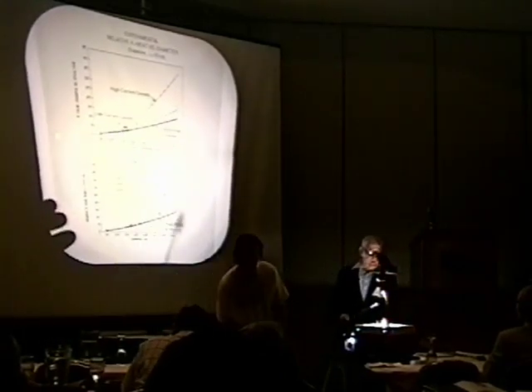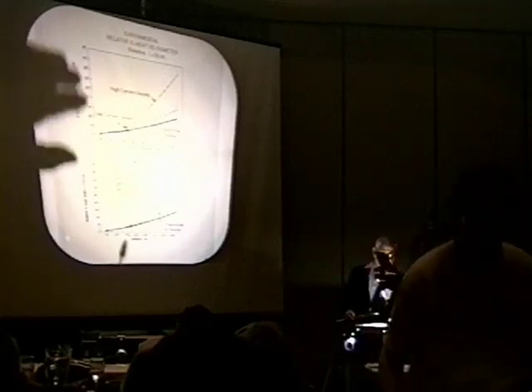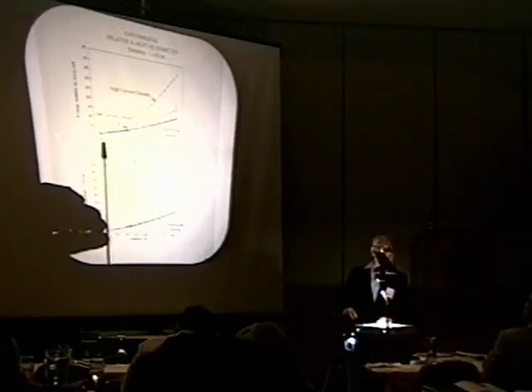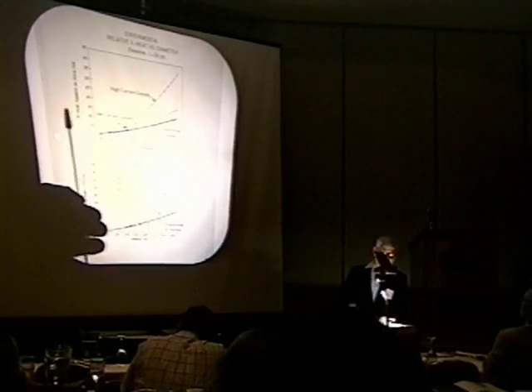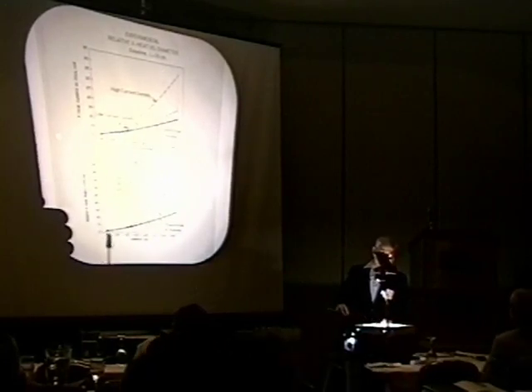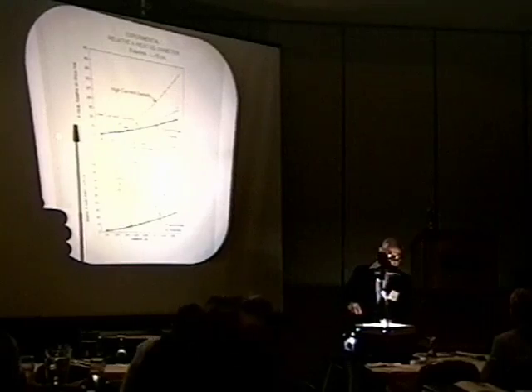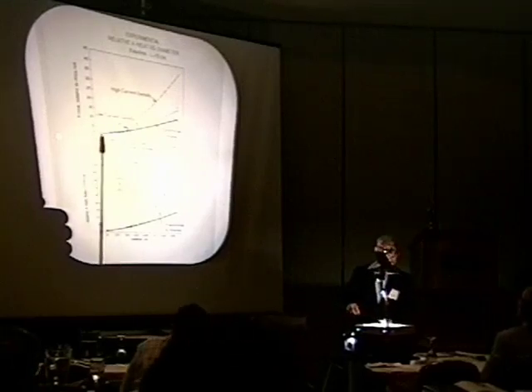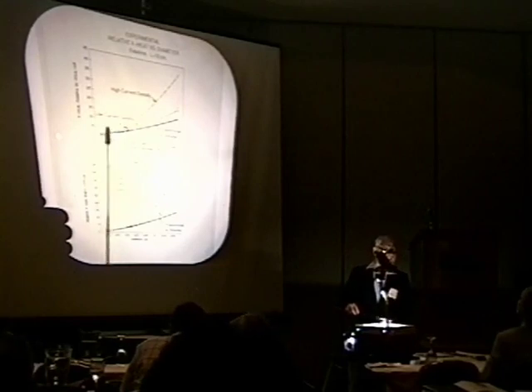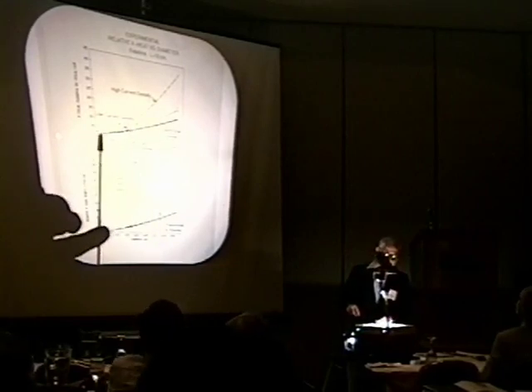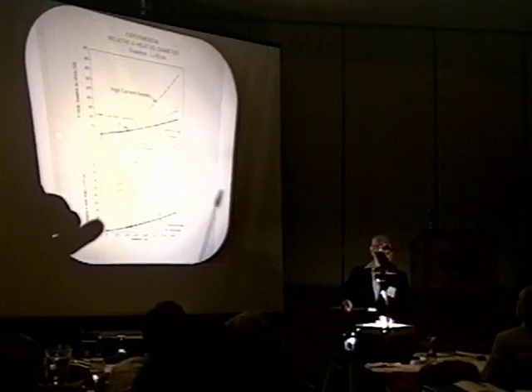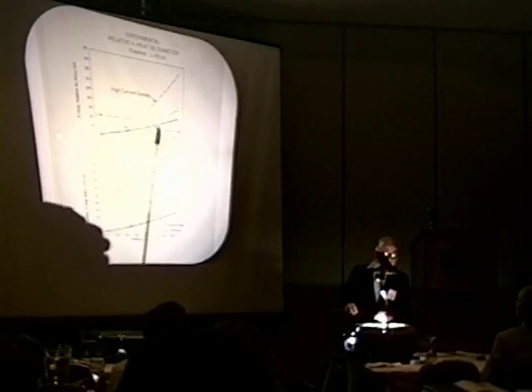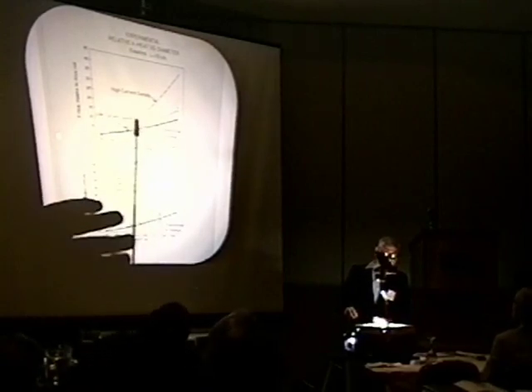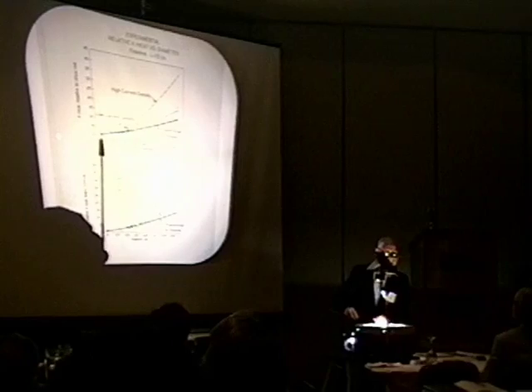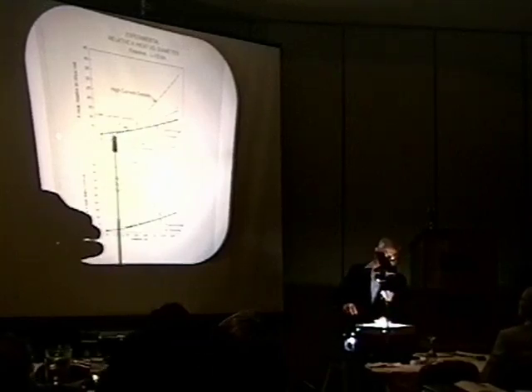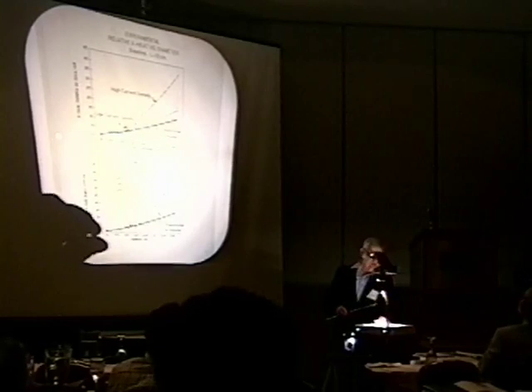But this is the same data, except we're plotting left to right is raw diameter. Top and bottom, this is experiment, this is the simulation, and the vertical scale is again excess heat relative to the 1/10 diameter. That is, at 1/10, the ratio of the heat to itself is 1. This is a comparison. At 2 millimeter, we take the ratio of the excess heat to that heat. Okay, and these are the experimental points, same ones shown here.